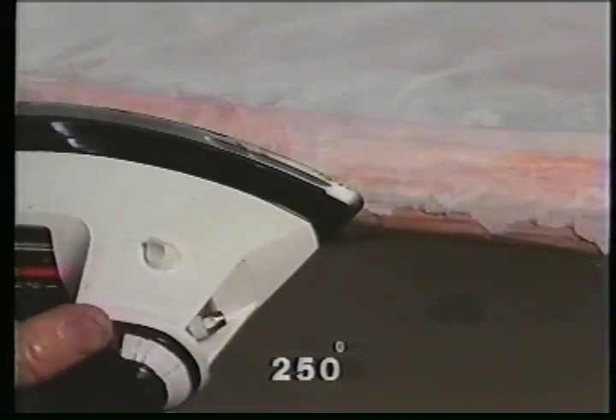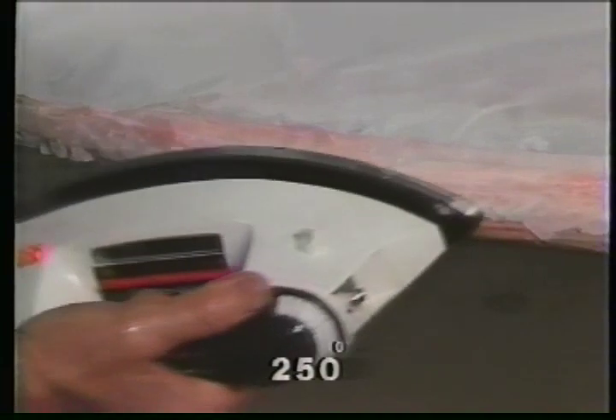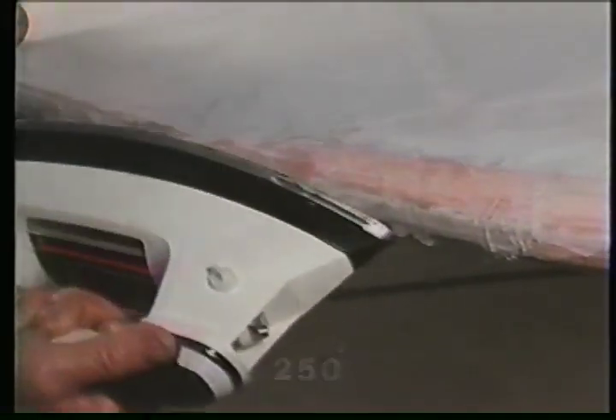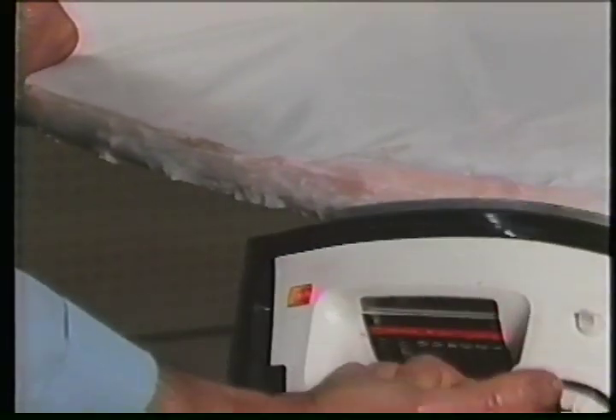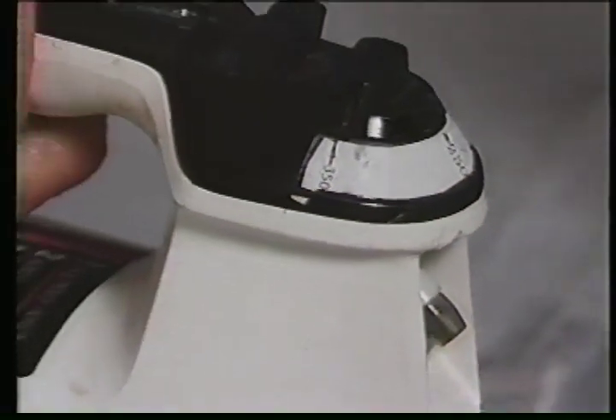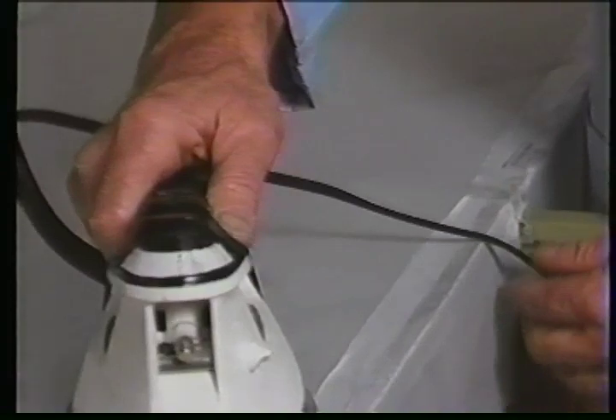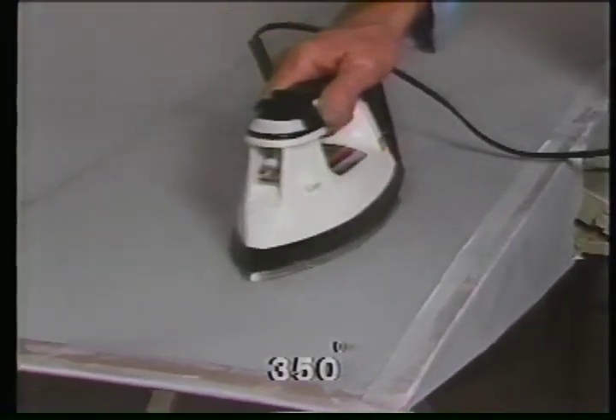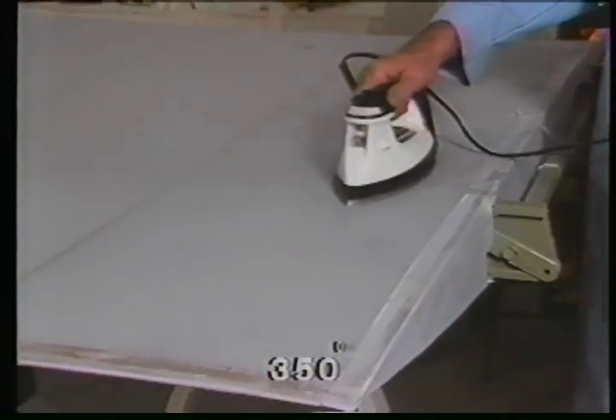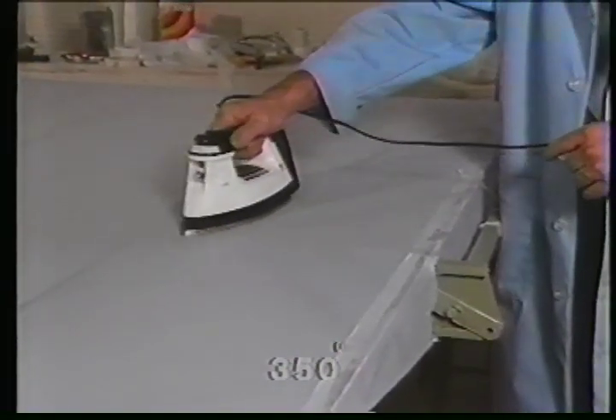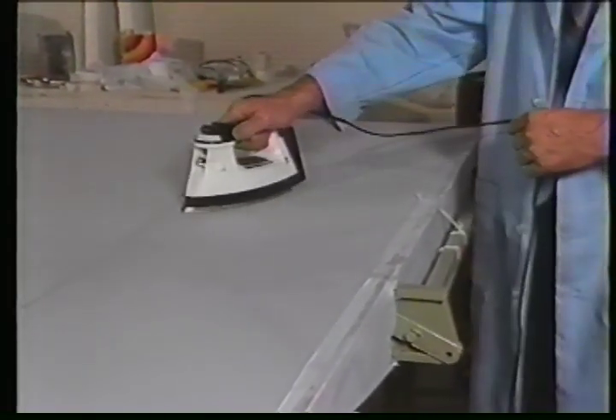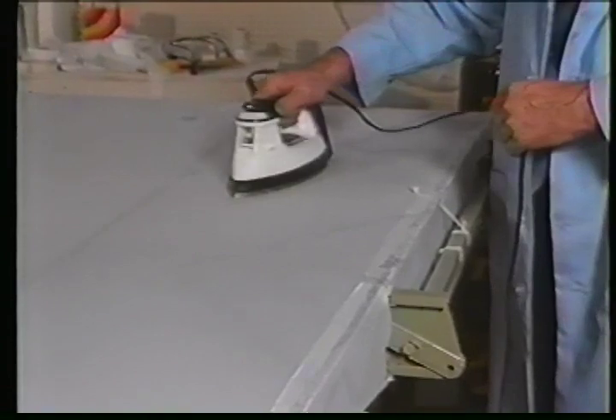The 250-degree temperature is used for the initial shrinking of fabric panels and to smooth wrinkles from overlap cement seams before final heat shrinking and remove creases while lightly tautening the fabric over plywood surfaces. The 350-degree temperature setting is used for the final panel shrinking to develop the maximum tension. The highest temperature in combination with the type and size of the filaments, the thread count, and fabric slack when installed determines the tension.